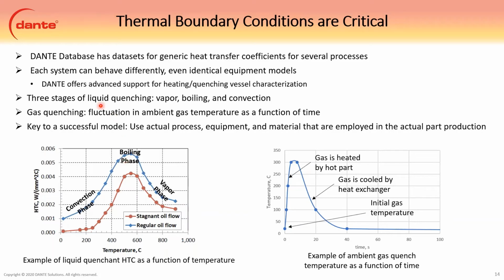Then we must also consider, particularly between the two different quenching methods, liquid and gas, there are some differences that you must consider. For liquid quenching, you have to consider the vapor phase, the boiling phase, and the convection phase, represented by the figure on the bottom left. These are as a function of part surface temperature. So when the surface is really hot, you're in a vapor, slower heat transfer. And then as your vapor breaks down, you get to nucleate boiling, which is your highest heat transfer. And then you slowly go down to pure convection.